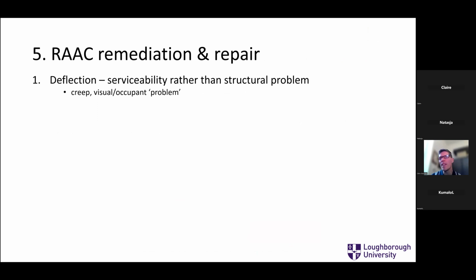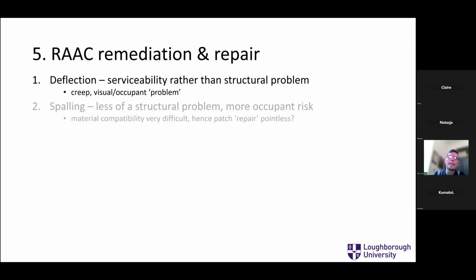Deflection is the obvious thing we see. We can see it deflecting, and this stuff does creep and deflect. But it's more of a serviceability problem rather than a structural problem. It's okay if it deflects a bit. It might exacerbate this problem we have at the bearing, but it'll never fail from bending too much. So we can correct the deflection fairly easy. We can prop it up, but sometimes that makes it worse because you've aggravated the plank.